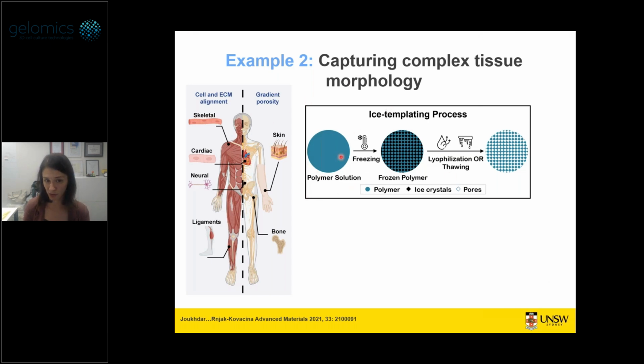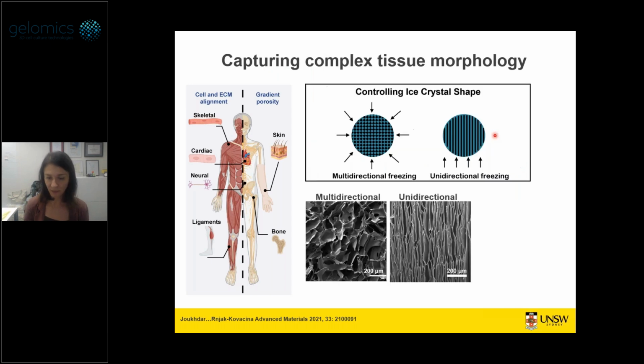So we start with a polymer solution, in our case, silk in water. We freeze it, and that causes ice crystal formation. And then when you remove those ice crystals, everywhere you had an ice crystal, you now have a pore. By changing the direction of the freezing, you can change the shape of those pores. So if you freeze in a regular freezer, freezing will happen from all directions, and you will get mostly rounded ice crystals and pores. And so you might get a scaffold that looks like this. This is our silk. And this might look like the extracellular matrix of skin, for example.